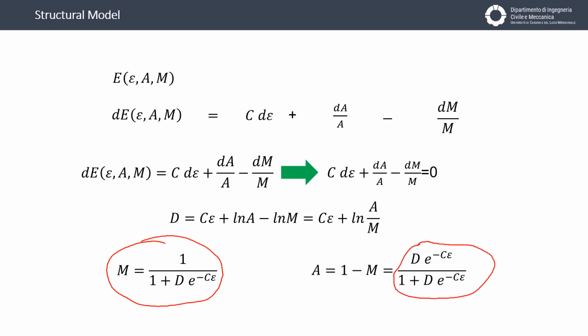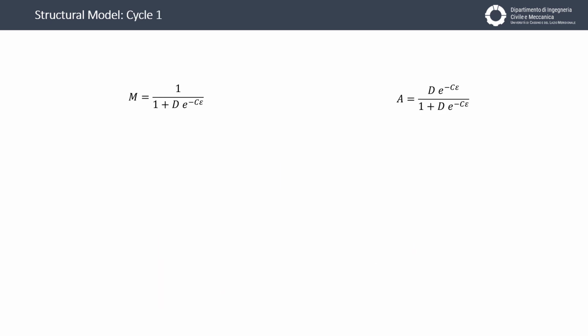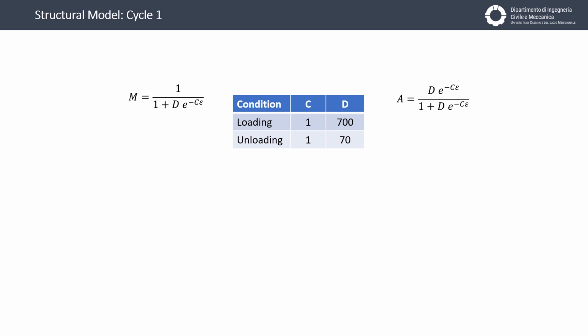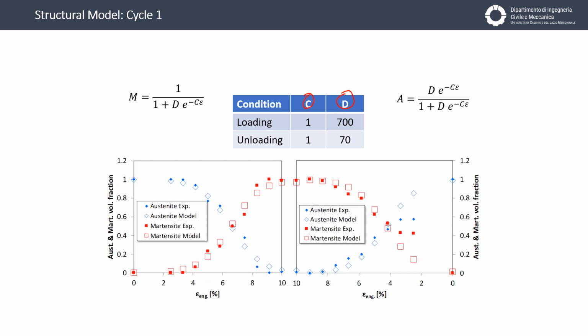These are the equations which calculate the quantity of martensite and austenite during a deformation process characterized by an epsilon level of deformation. Considering the results in terms of quantity of martensite and austenite taken from the step-by-step tests in loading and unloading conditions at the first cycle, we can calculate the values of the parameters C and D. You can see that C is always equal to 1 and D changes from 700 to 70, and in this case the parameter D takes into account the hysteresis of the material.